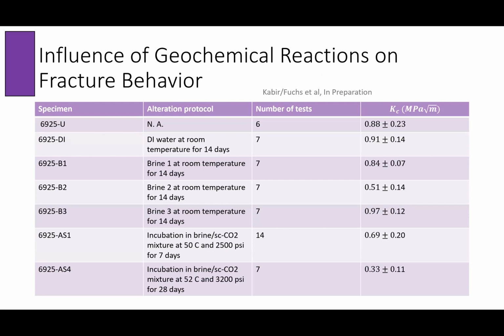So we have the different conditions where we started with a lower chemistry, DI water, brine 1, brine 2, brine 3, and then we're going to have a complex chemistry, brine saturated with supercritical CO2 at high temperature and high pressure. What we can see is that we start with a very high fracture toughness, and overall we have a decrease. So when we incubate just in the brine at room temperature, we still see a slight decrease, especially more pronounced for brine 2, where we have a strong ionic strength.